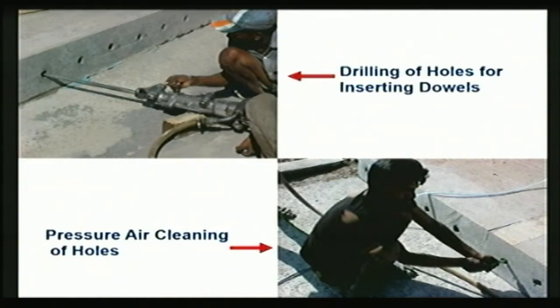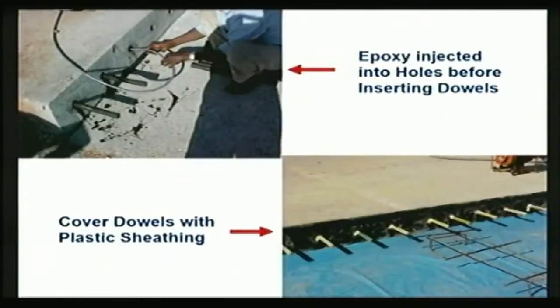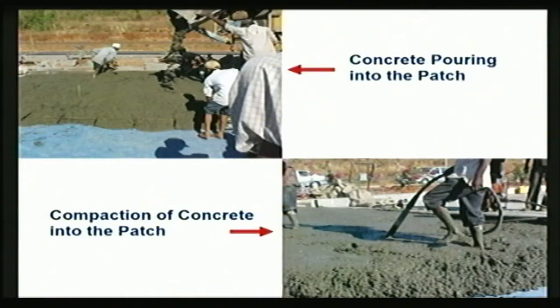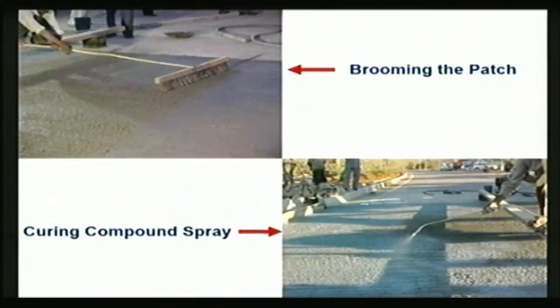So you have to insert the dowel bar: first create the dowel holes, then clean the dust out, and then neat epoxy is inserted into the dowel holes, and then dowel bars are fixed. You can place the sheathing caps or plastic caps over the dowel bars, and if the subbase is also damaged, you repair the subbase also, and then fill it with fresh concrete, compact it, texture it, and use some curing compounds so that plastic shrinkage cracking can be avoided.